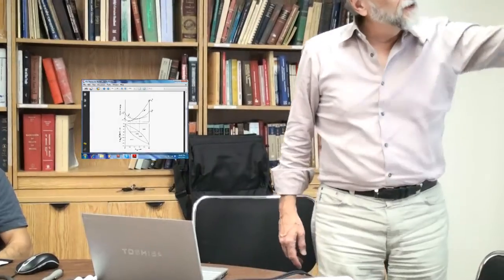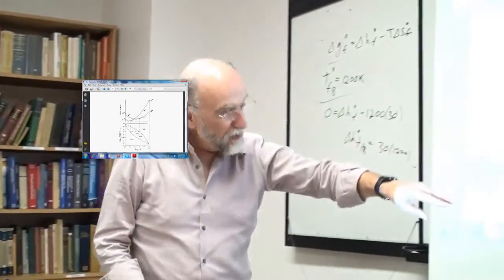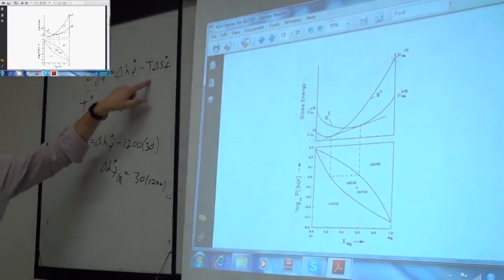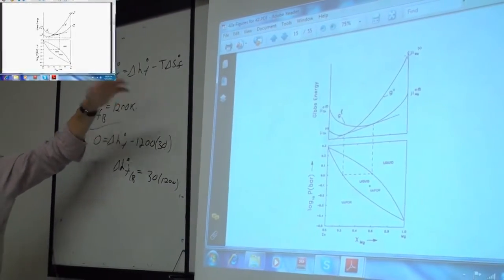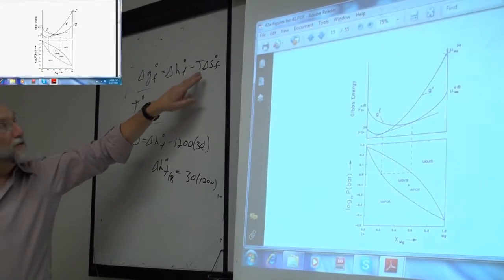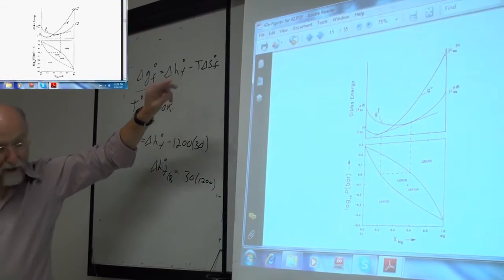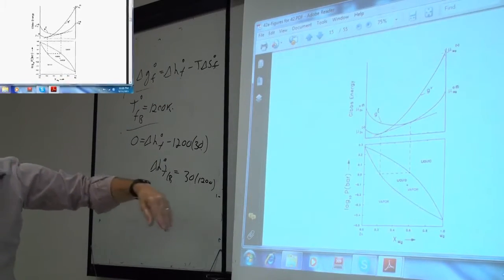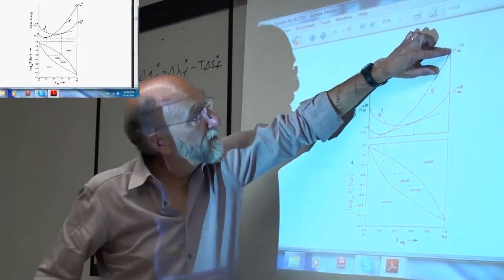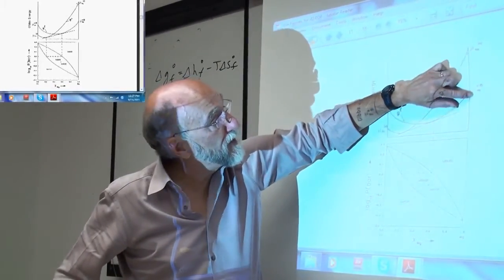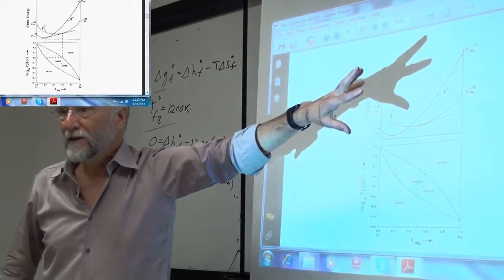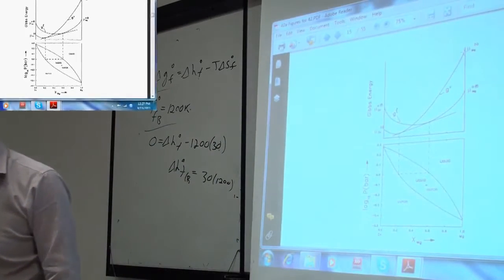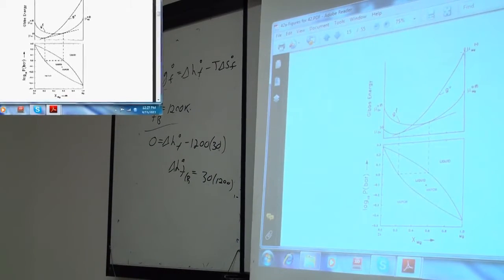So what we have to do now is, when we were doing this in terms of temperature, at constant pressure, we had to find an expression for this difference in terms of temperature, and this is what we came up with. It's delta H minus T delta S. So that shows you how those endpoints vary with temperature when pressure is constant. Now if we're trying to calculate this diagram, we have to come up with how the difference between the chemical potential of the vapor and the liquid varies with pressure. So how the Gibbs energy of vaporization changes with pressure, right?